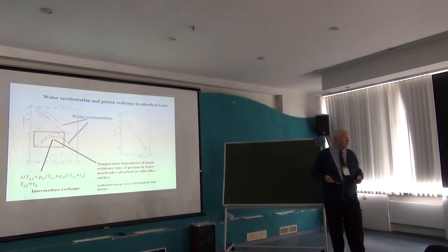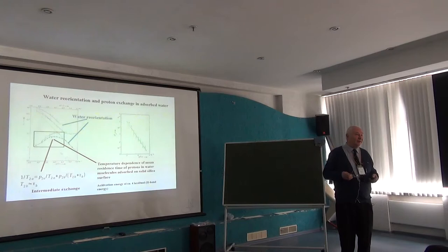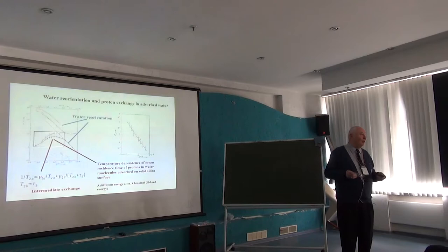In summary, we have different types of water molecules. We can directly observe quantitatively the lifetime with respect to exchange in the hydrogen bond. But we can also observe the correlation time for the reorientation. We can even give a very direct measure of the activation energy for the proton exchange. This work is not very widely recognized, but with respect to many publications, the results are not always correct, and it seems necessary to remember this relatively old work.